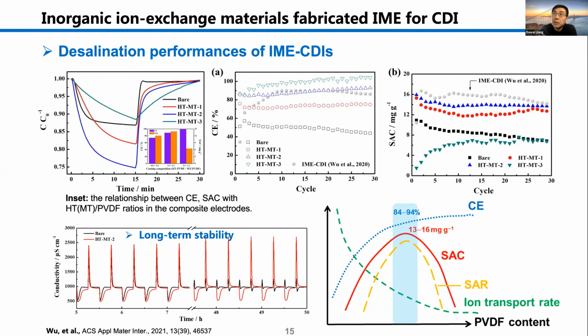This is the desalination performance of the CDI with the composite electrode. The PVDF binder blocks the co-ion, resulting in high CE. So with the increasing of the PVDF content, you could get increasing CE, reaching about 84% to 94%. But the PVDF also could decrease the ion transport rate, so you need to compromise between these two. You could get a maximum specific adsorption capacity of about 13 to 16 milligram per gram, and also the highest specific adsorption rate at a certain PVDF concentration.